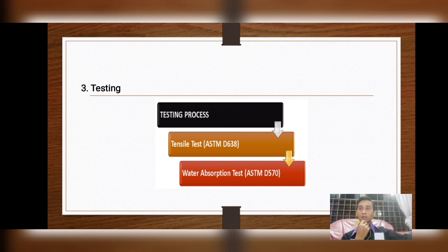After that, all of the 8 samples are dried in the oven for 6 hours. The temperature set for the oven is 105 degrees, and after 6 hours, the dried samples are brought out from the oven to be weighed. All of the 8 samples need to be weighed 3 times, and the average weight for each of the samples is recorded. The thickness for each of the samples was also taken before the test. Then the samples were put in a small container which contains distilled water, and the absorption test begins for 2 hours.